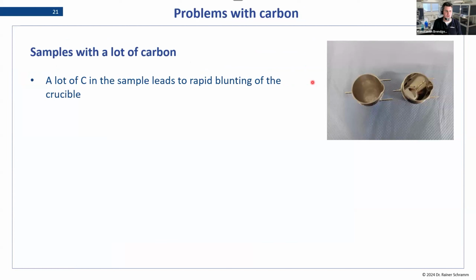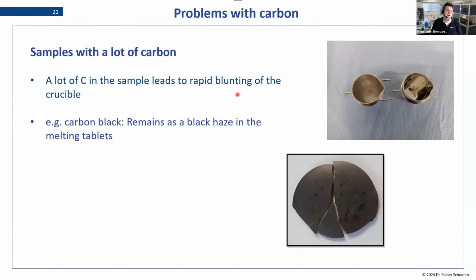The effect of carbon, again, just a few examples. I mentioned before that carbon causes increased wear, and you can see this here. This is a new crucible, and this is one that has done a few hundred samples. With samples that contain a lot of carbon, you can see this happen very quickly. It's not necessarily a problem, but you want to make sure that you recycle your platinumware more often then. How do we find out if our sample has carbon? Well, if you're doing a fusion and it comes out like this, that means there is a lot of carbon in your sample and it has this haze basically.